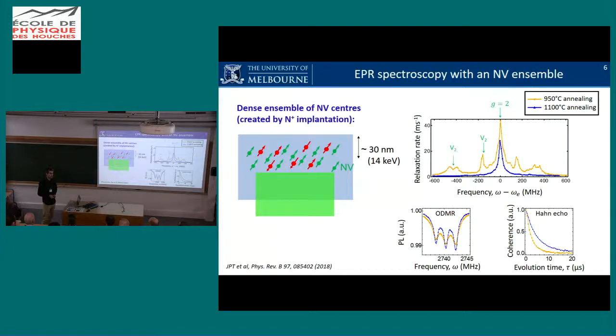Phononic decay, no. So here, the cause for this short T1 might be phononic related, yeah, sure. But you don't see that in very deep NVs in type 1b, for instance. It's all very narrow, and here it's very broad, and it could be also related to the surface. Yeah, possibly. So I think that's actually a good illustration of how useful this technique is for this particular situation where you have very short-lived species.